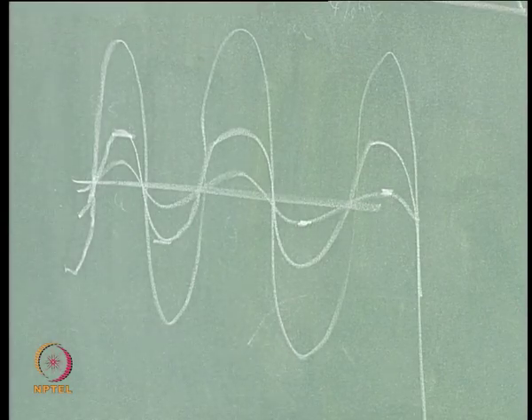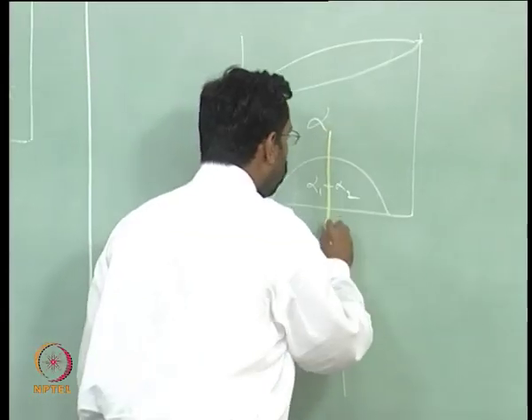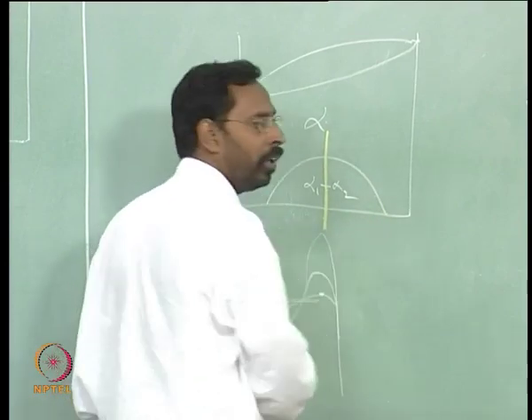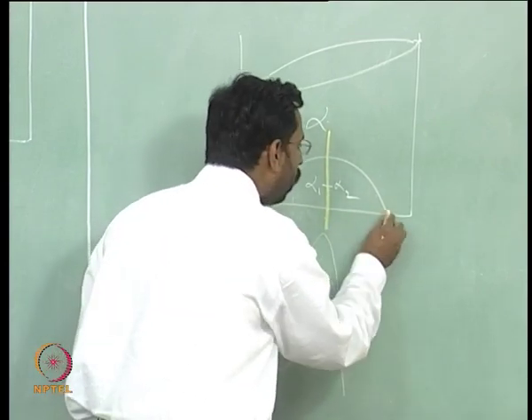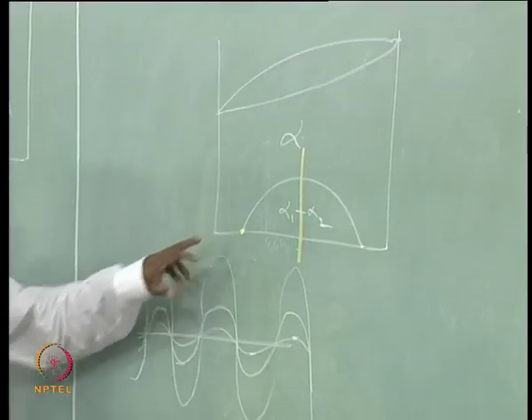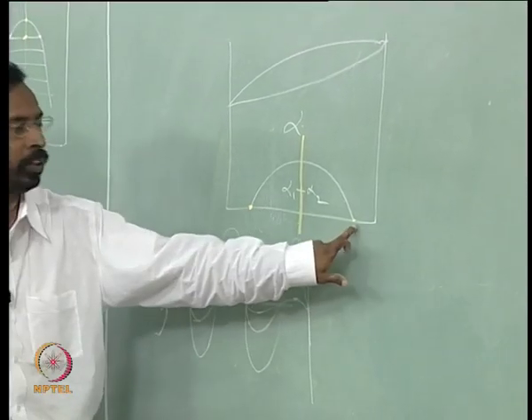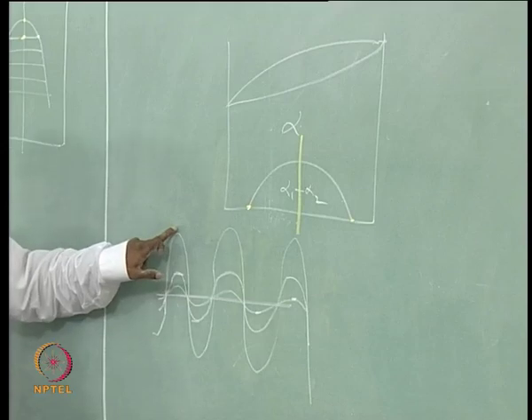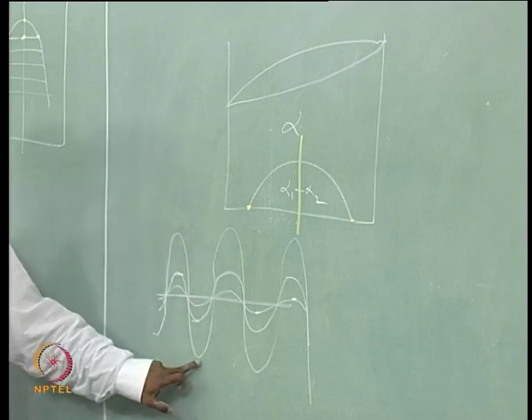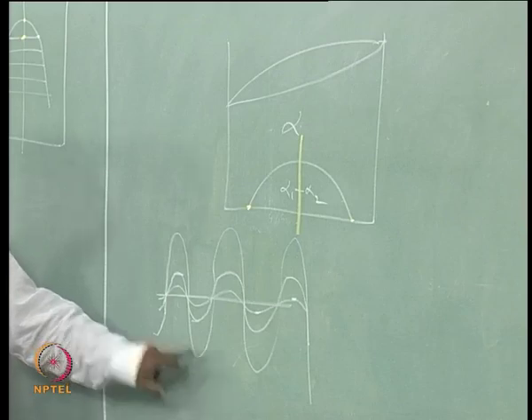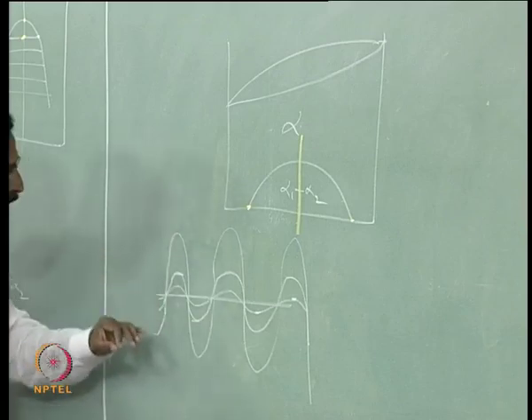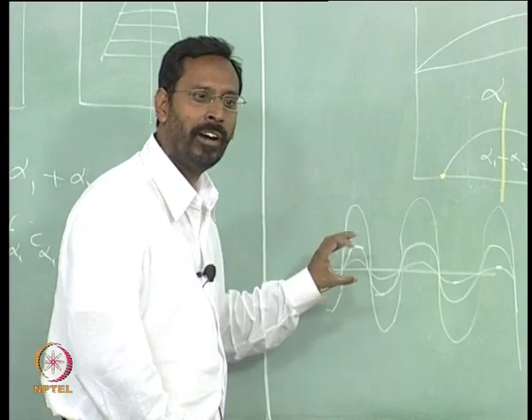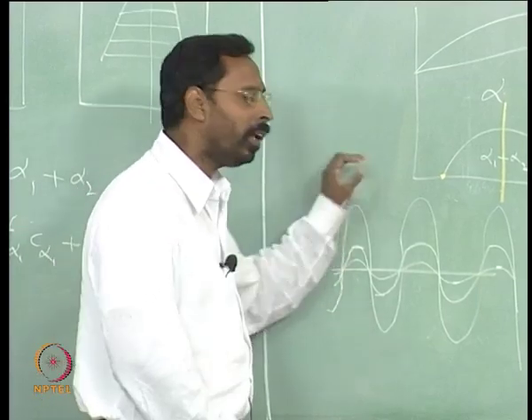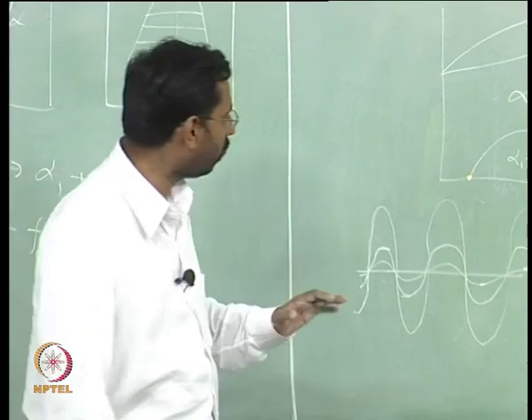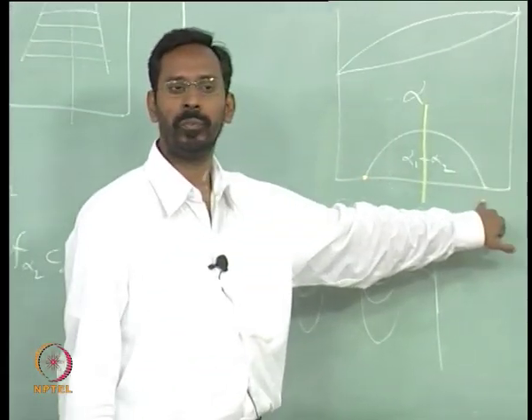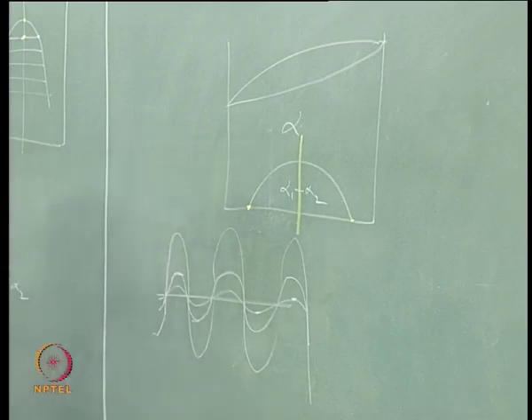that finally, if I take that alloy and hold it at room temperature, it will keep on growing until alpha 1 achieves this composition and alpha 2 achieves this composition. The lower is alpha 1, the higher is alpha 2. So this compositional wave will keep on changing its amplitude to such an extent that finally you reach this value, and this is what happens whenever you have this.